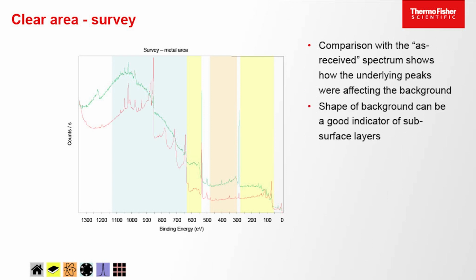So what we want to do is clean the sample to get rid of that carbon so we can actually start to understand what's there. And so we give it a bit of an etch with the ion source on the system. So this is using monatomic argon ions, hitting the surface, knocking off material very slowly. So we're removing material at a few angstroms per second. And as we clean it off, remember which way around this is. Yes, the red one is the new spectrum now.